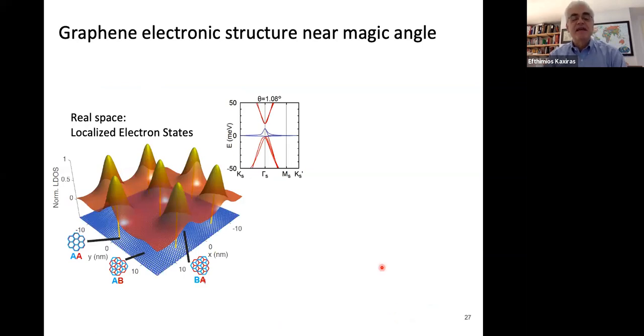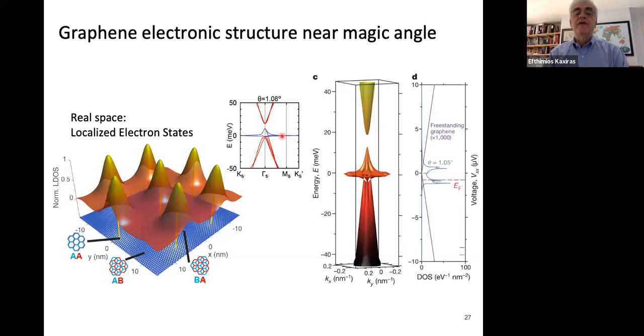This is what happens in the bilayer system. In real space, you have highly localized electrons. So this is the number of electrons in real space as they are distributed in the actual graphene system. And you see this very high concentration. And it so happens that these peaks in concentration of electrons are in the areas where you have AA stacking. This is the high energy stacking of the two layers. And in momentum space, you see these very flat bands near the Fermi level.